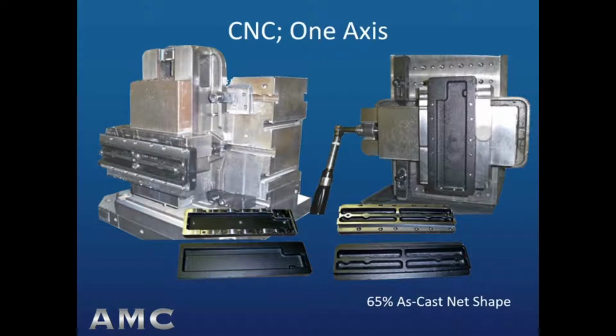The 2 similar fixtures are required to access each side of the cover. This casting is about 65% as cast net shape, which is on the low end of as cast versus machine features. The inset below shows each side of the casting prior to and after machining. Although it's a simple casting, there is an important fixture design consideration to be illustrated here.